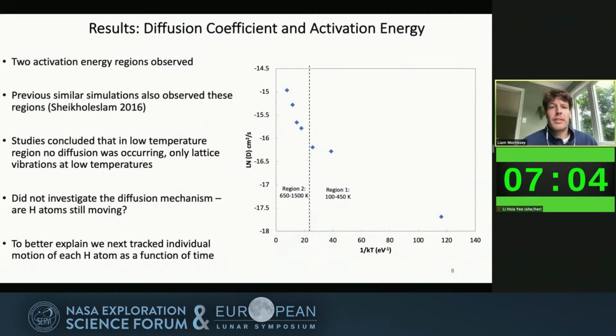So first, you can see on the right, we have a standard Arrhenius plot, which we can use to track the diffusion coefficients and the activation energies. Now, we actually observed 2 activation energy regions, one in the low temperature region between 100 and 450 K, and one was a higher temperature region. Now, previous similar studies on H diffusion in silicates have also observed these regions. But what's interesting is that this study said that the movement or the diffusion in that low temperature region was actually not diffusion, but only lattice vibrations found at low temperatures.